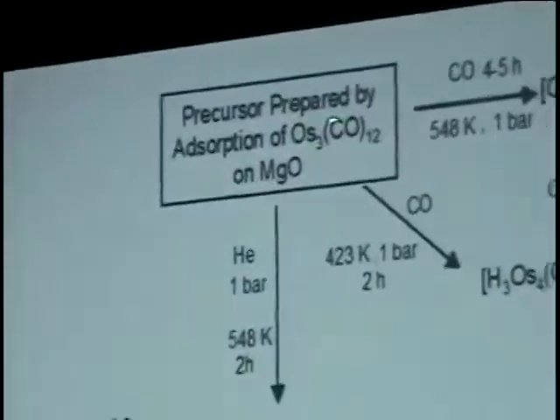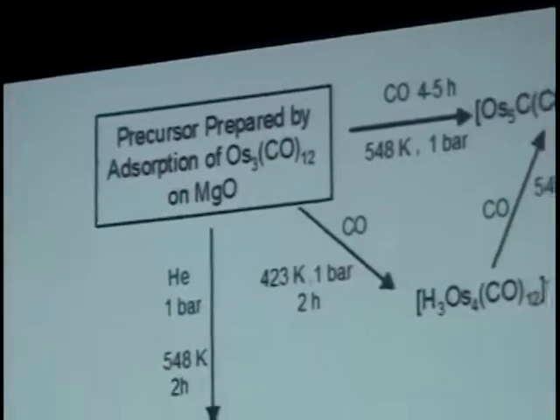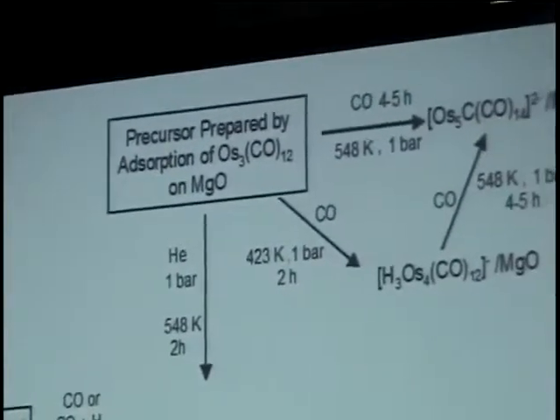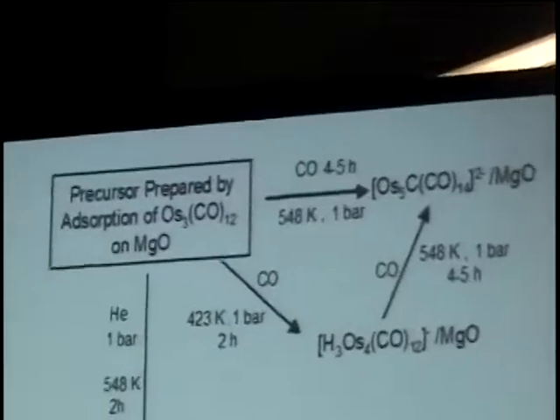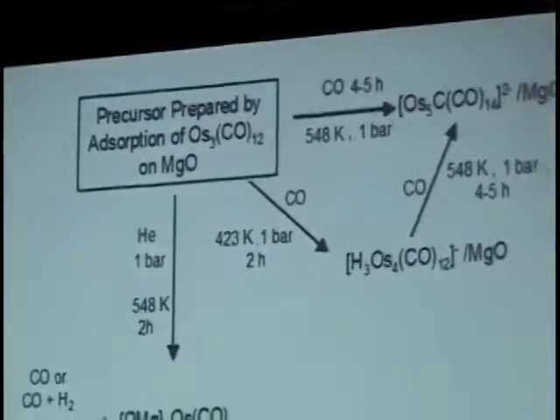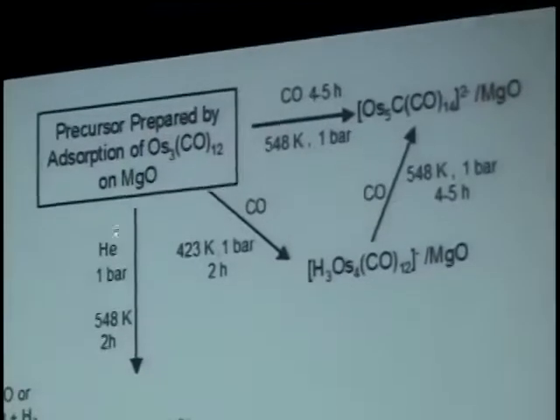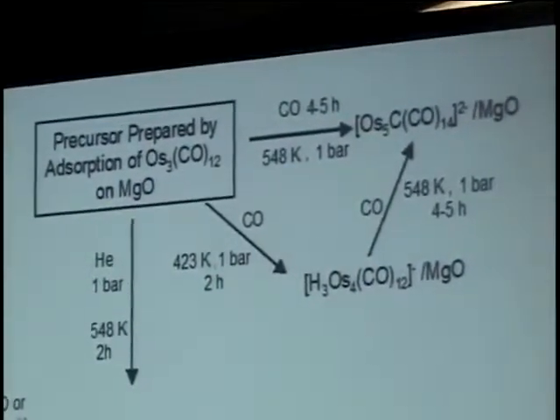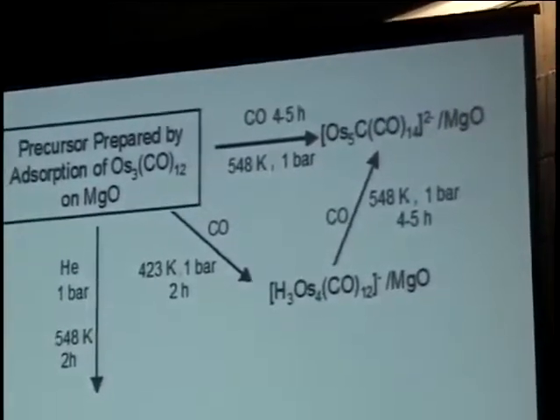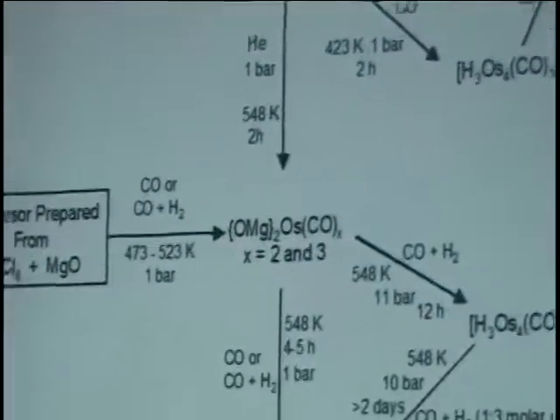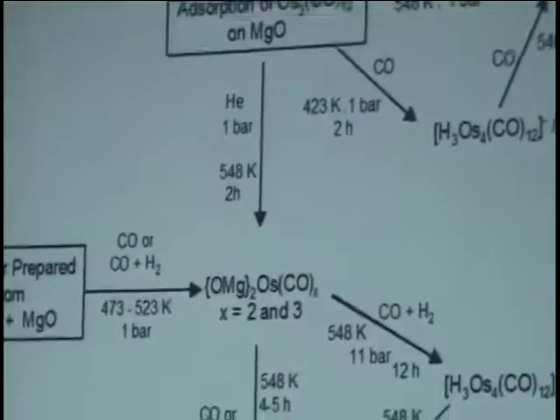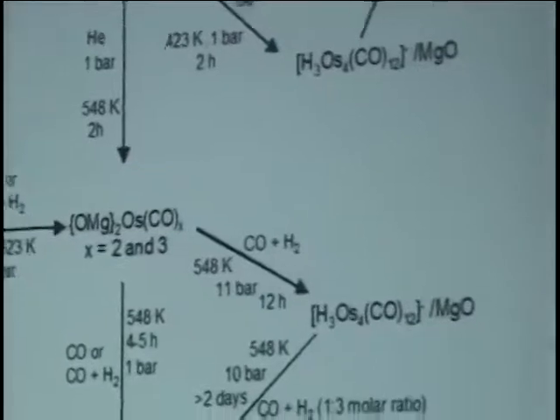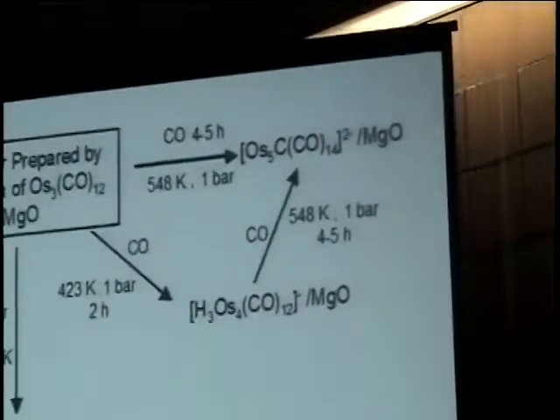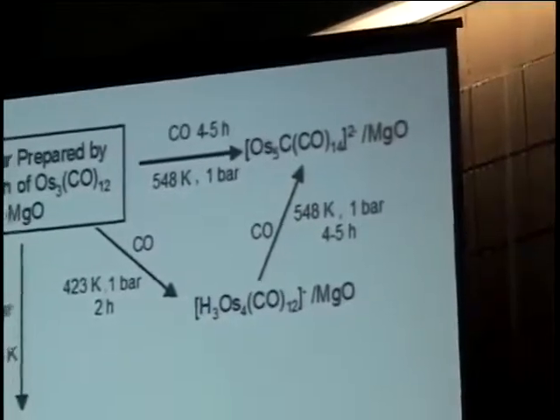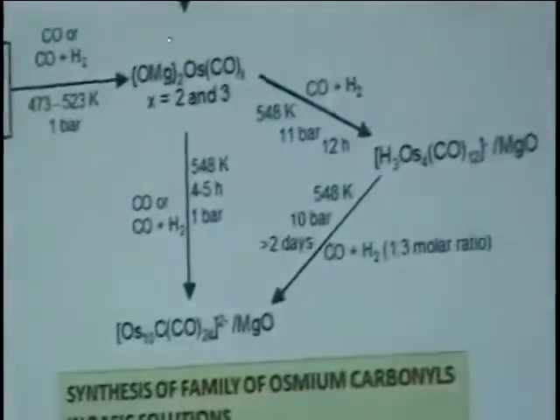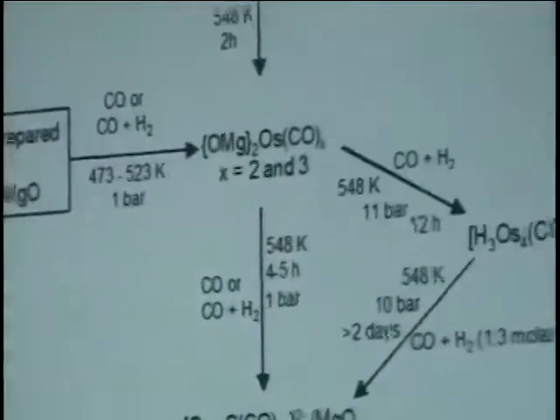So if we start with our parent compound, the triosmium carbonyl, with its triangular metal frame, we can oxidatively fragment it. So if it's adsorbed, or something that forms from it, which we'll talk about in a minute, if it's adsorbed on MgO and treated even under these fairly mild, oxidative conditions, you do the same thing by exposing it to air, but it's the hydroxyl groups on the MgO that are the oxidizing agents that oxidatively fragment the cluster carbonyl to give a mononuclear, that is a single metal atom, osmium carbonyl. So if you keep this in mind, this is a single metal atom with a couple of carbonyl ligands bonded to it.